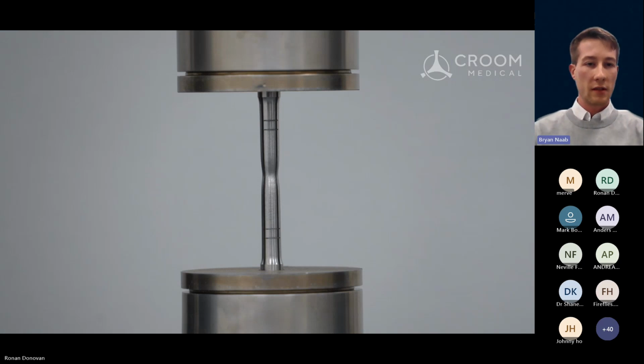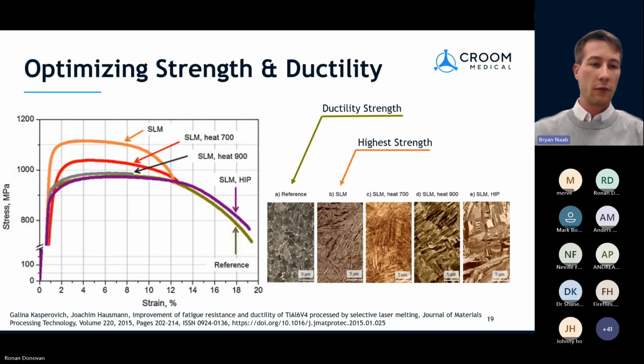So here's a video of a tensile test. Basically, we use a standard specimen, which is agreed upon by standards, and we will mount it in a servo-hydraulic test rig, which will then pull the sample apart, applying a tensile load as it's measuring the applied force and extension. And we can then use that data, so that force and extension, to plot what's called a stress-strain curve. A stress-strain curve is kind of like a characteristic fingerprint for a material's mechanical strength and ductility.